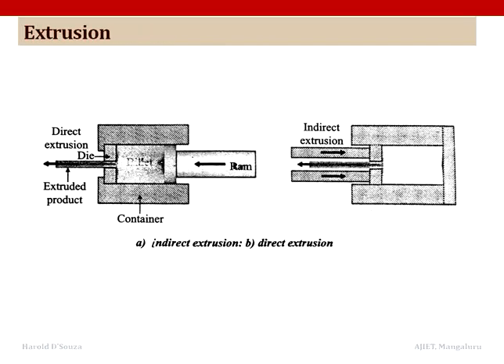Extrusion. This is a procedure of metal powder compaction or semi-products manufactured by pre-pressing or possibly by pre-sintering in continuous strands. The process can be carried out at a normal or elevated temperature or the sintering temperature. Now in the case of extrusion, pressing at normal temperature, a mixture of powder and a plastificator is pressed through a nozzle into the rods or tubular forms.